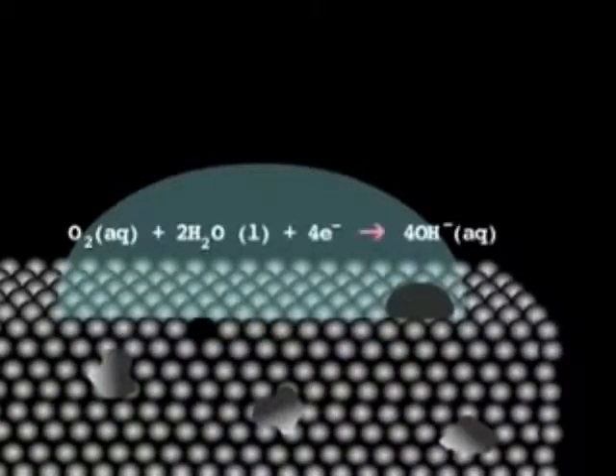The oxygen readily reacts with water to form hydroxide ions. At the same time, the iron atom gives up two electrons to become an iron 2 ion, which is repelled out of the lattice and dissolves into the aqueous solution. Without access to this solution, there's no way for iron 2 ions to be formed. This explains why rusting happens much more slowly in dry conditions. Pitting can be one of the most dangerous forms of corrosion because it is difficult to anticipate and prevent, relatively difficult to detect, occurs very rapidly, and penetrates a metal without causing it to lose a significant amount of weight.